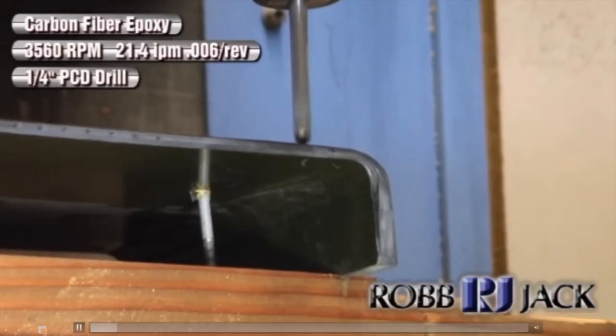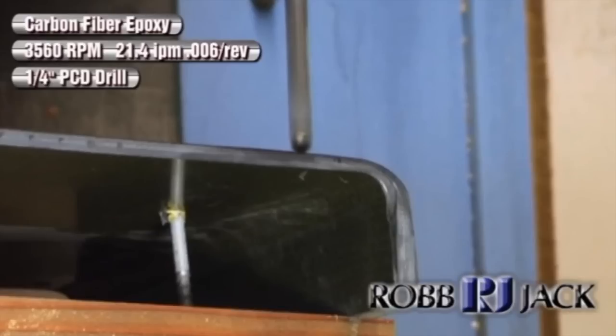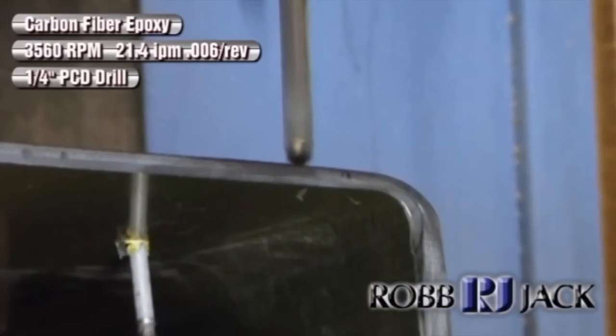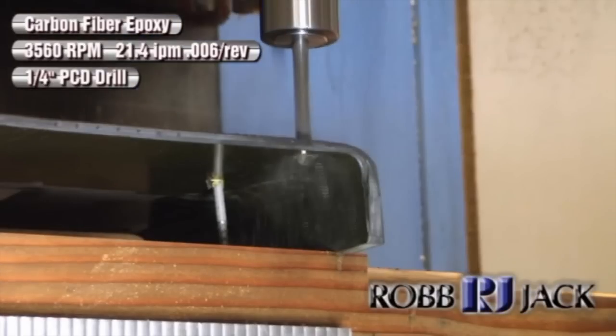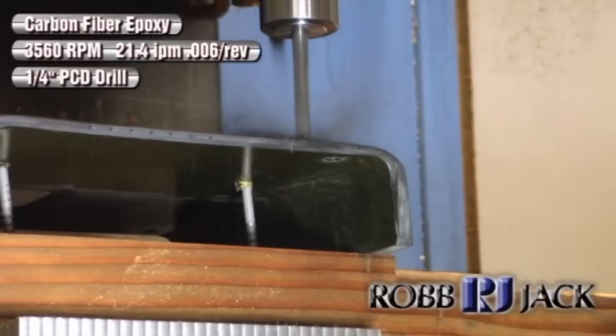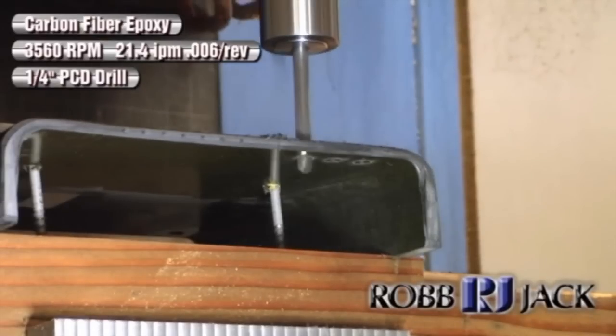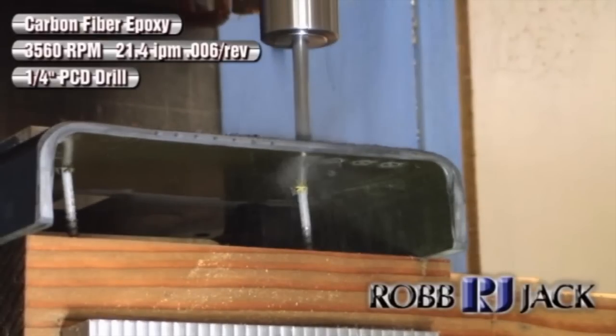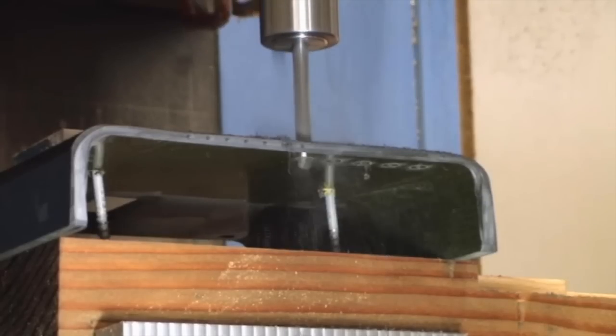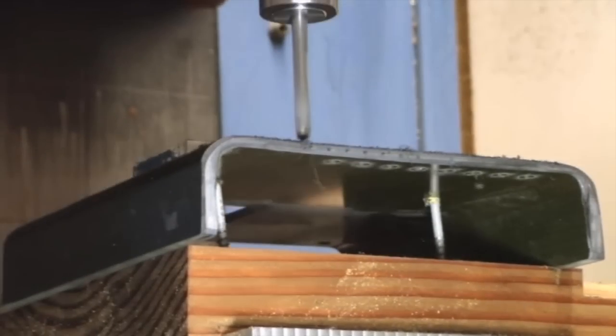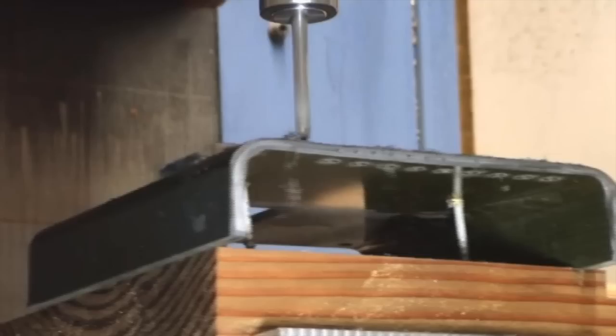So to note when you're watching the video, the holes that we're going to do, look at the exit hole. We're able to make these holes very quickly at a fast feed rate with no delamination or uncut fibers at the back side. That little white ring that you're seeing, that's just the dust that's being deposited on there.